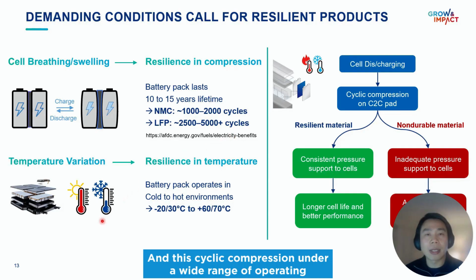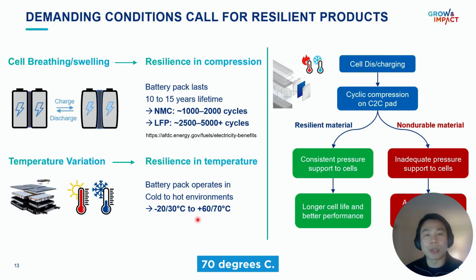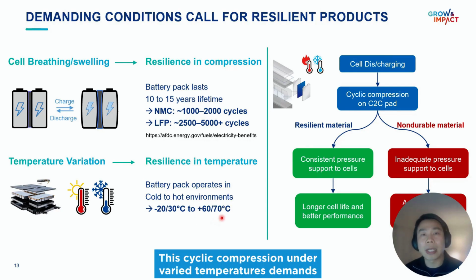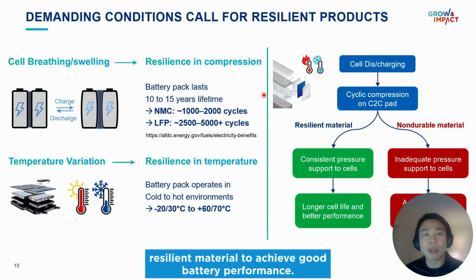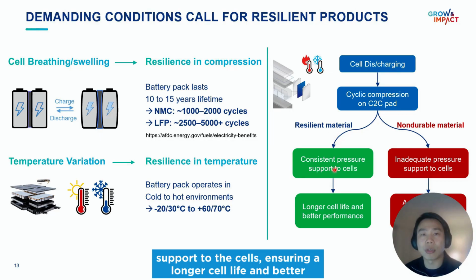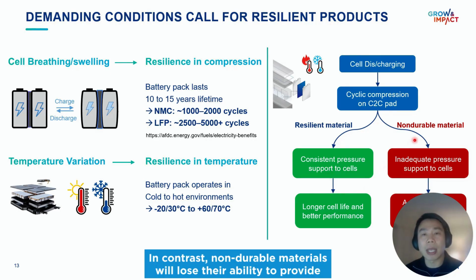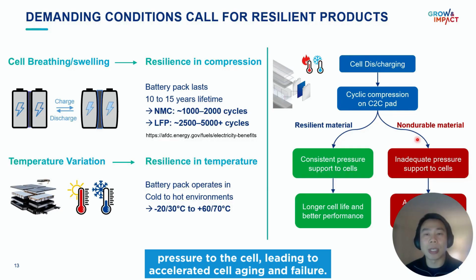And this cyclic compression occurs under a wide range of operating temperatures, from sub-zero to very hot temperatures up to 60 or 70 degrees C. This cyclic compression under extreme temperatures demands resilient material to achieve good battery performance, because a resilient material can maintain consistent pressure support to the cells, ensuring a longer cell life and better performance. In contrast, non-durable materials will lose their ability to provide pressure to the cell, leading to accelerated cell aging and failure.